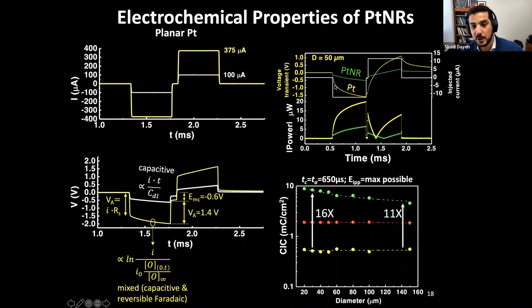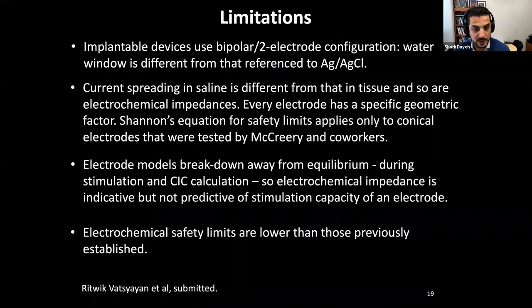Basically, if we flow the same amount of current, which is the biphasic pulse, into a platinum contact or a platinum nanorod contact, we build across the electrode a smaller potential on the platinum nanorod compared to platinum, and therefore the power consumed is lower than that with the platinum. So we can have a longer battery life for implants that use low impedance electrodes.